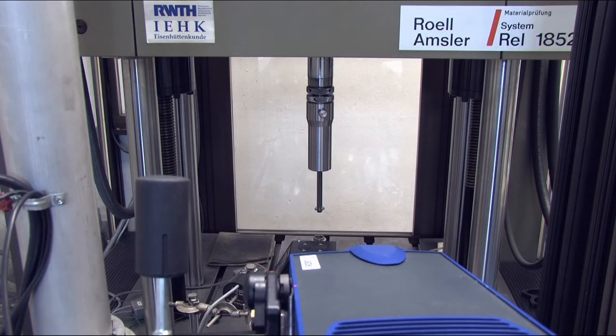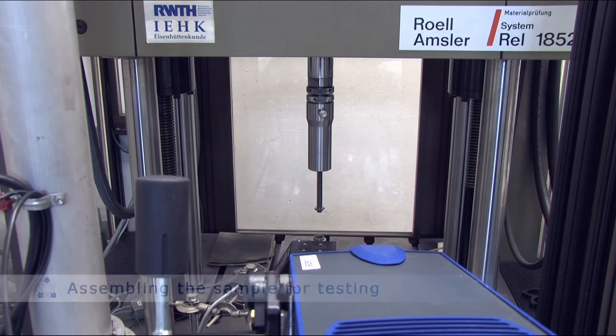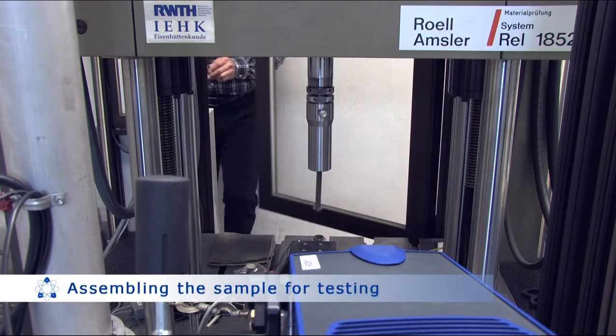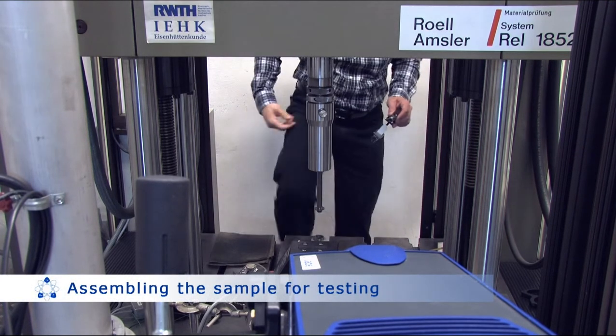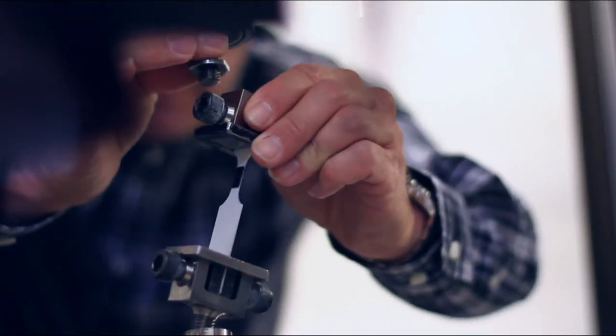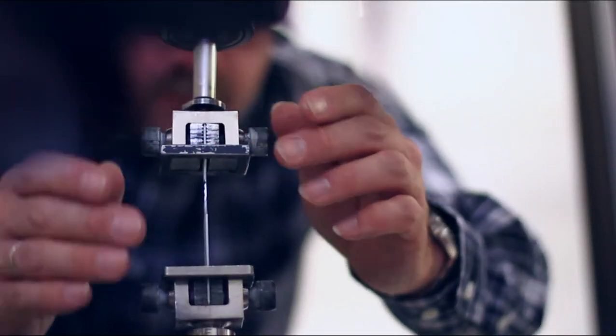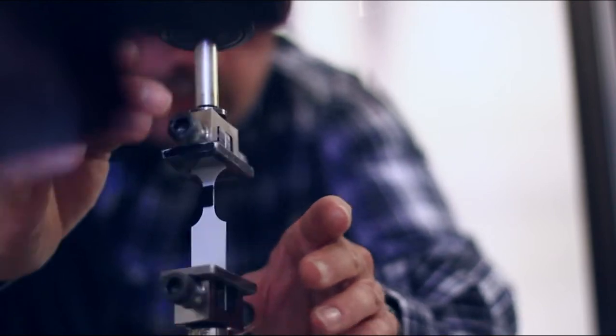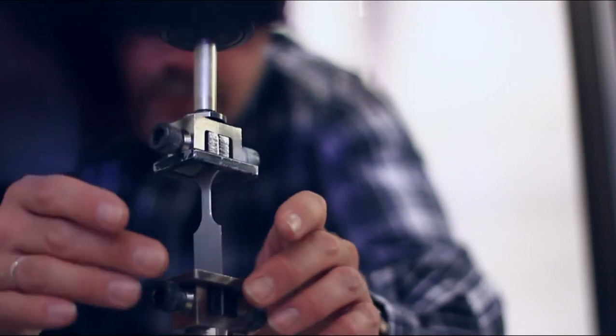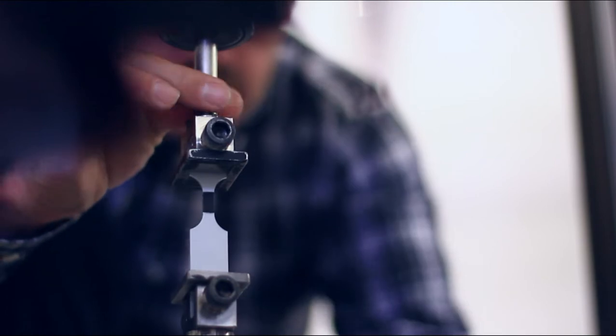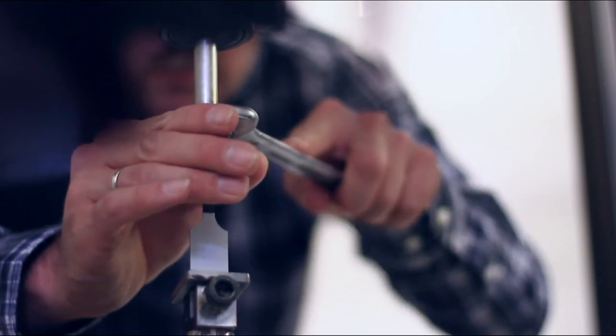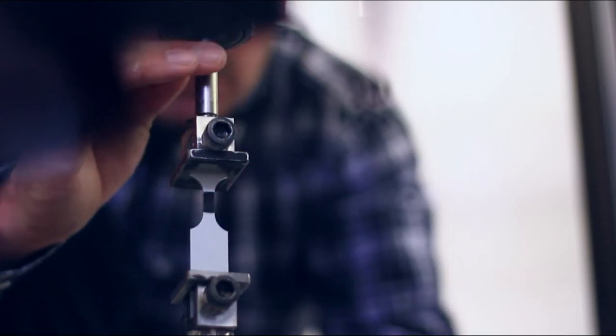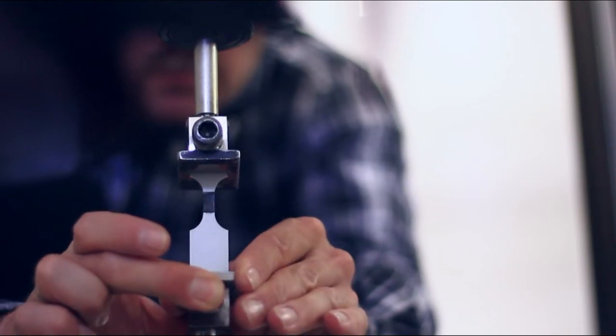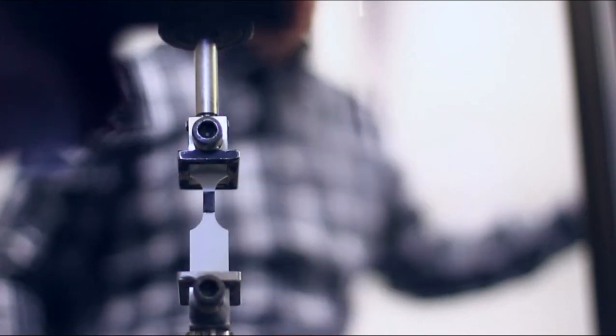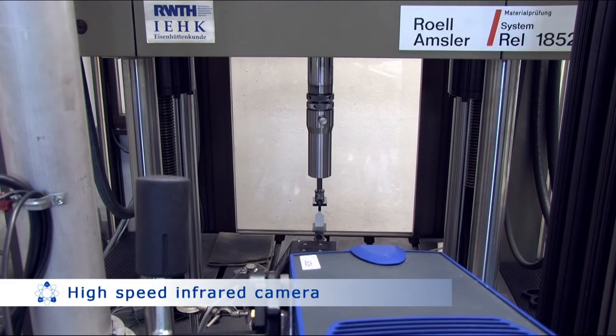The high strain rate tests are performed on the servo-hydraulic high strain rate testing machine according to SEP 1230. The tests are performed to characterize the material's behavior under crash conditions, especially for the automotive industry. In the context of material testing, the rise in temperature affects the results. Hence, at the Institute of Ferrous Metallurgy, the sample warming during testing is measured with a high-speed thermographic camera.